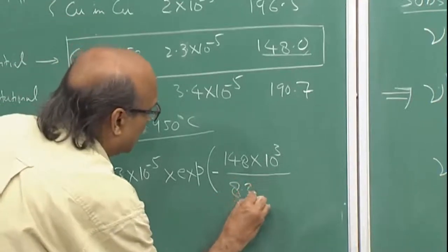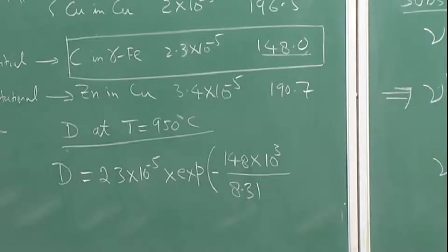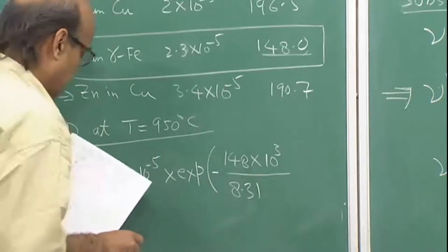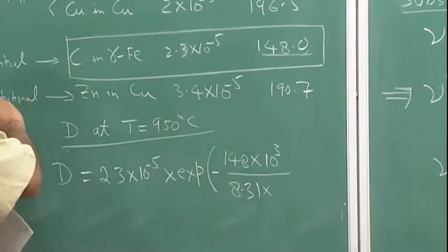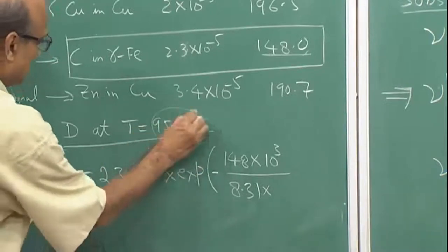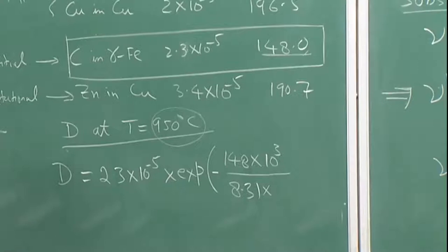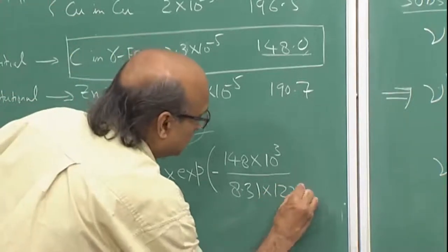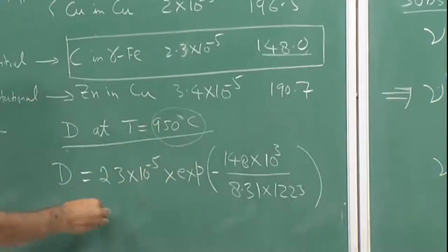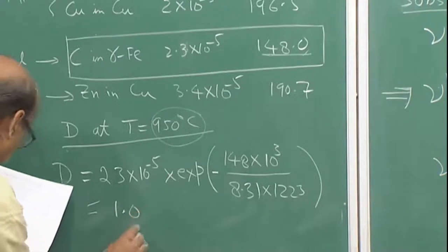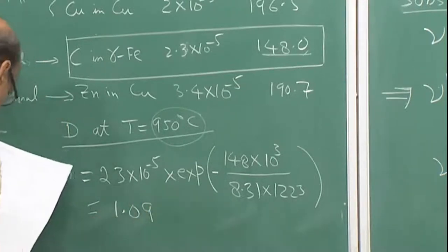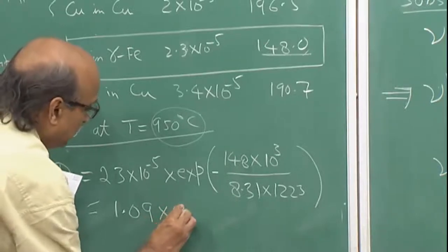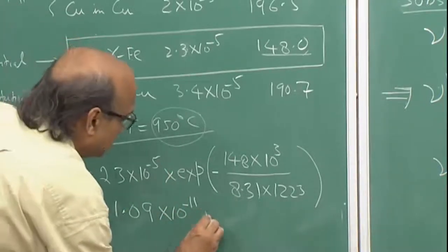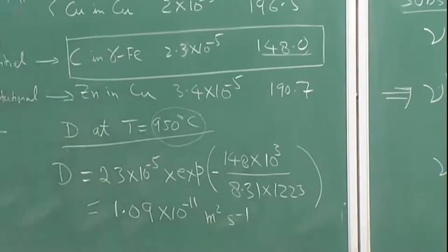divided by the gas constant, which I am going to take as 8.31 joules per Kelvin, times the temperature in Kelvin. So, I have a temperature of 950 degrees centigrade, add 273 to give me 1223 Kelvin as the temperature. I calculate this and I get a diffusion coefficient value at 950 degrees centigrade for carbon in gamma iron as 1.09 into 10 to the power minus 11 meter square per second.